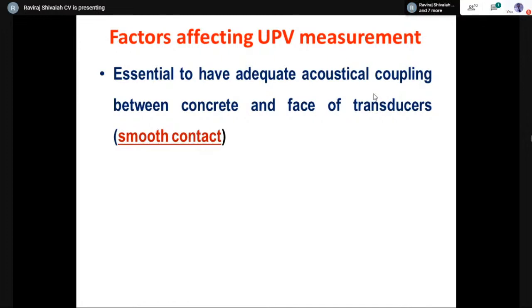Again, I'm trying to remind you that the transducers should be kept on the concrete. It should not be kept on the mortar. If we are testing a column, you have to remove the plaster and then smoothen the surface. You can use a carborundum stone, or you can use a small grinding apparatus. You have to grind and smoothen the surface, and then use the instrument, the transducers.